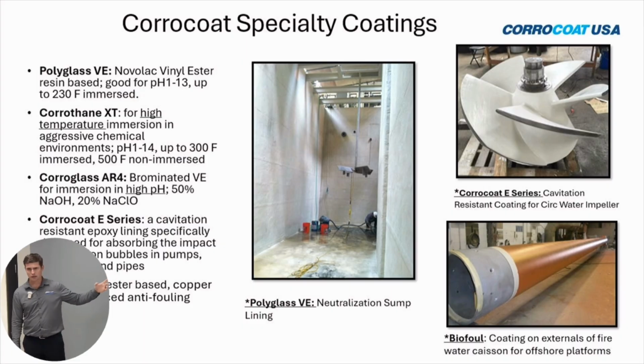And then biofoul. All of you are inland. Do you have any situations where you're dealing with fouling and you're looking for anti-fouling, maybe for your cooling water systems or firewater piping? Yeah, so the biofoul is a polyester resin-based coating that utilizes elemental copper flake. The copper emits ions, which the biological growth will not adhere to. So it's not like your traditional anti-foulant, which is ablative, which has multiple colors and multiple coats, and the fouling just peel it off. And then you get to green and you say, I need to coat again. This is a fully functional, long-lasting barrier coating.